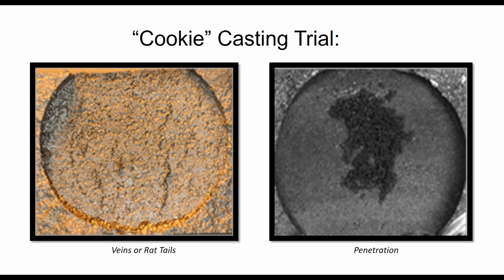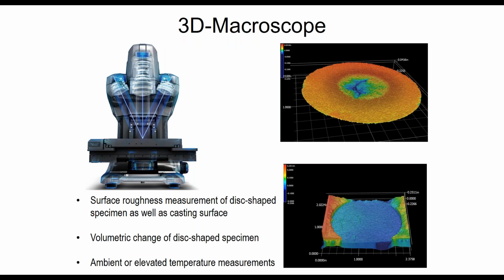These particular terminology are foundry defect terms. You're not going to find them very well if you Google them. The point is, we want to prevent this and as well as get a superior surface roughness relative to the as-cast surface. That is important. We can evidence this today non-contact. With technologies like I'm showing you here, a 3D macroscope could show us what is happening on our disc-shaped specimens in the molding room. And then in the finishing room, we can see this on the casting.